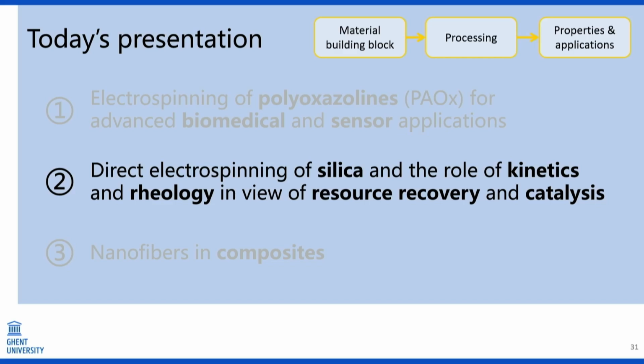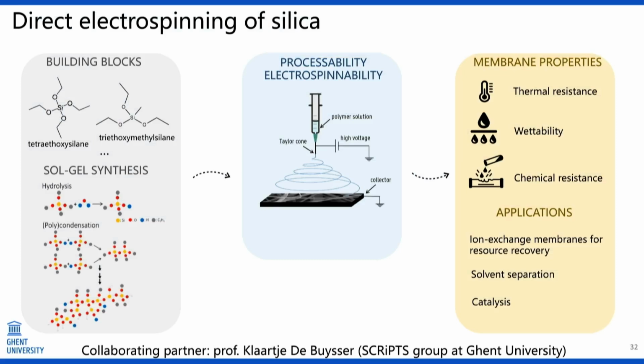So then let's move to a completely different building block system, the silica. We use that because of its interesting properties: very high thermal stability of silica membranes and chemical resistance. So for completely different applications, where we focus more on resource recovery and catalysis. Our strategy in spinning silica is a bit different from many in literature. We did not use co-spinning with an organic polymer.